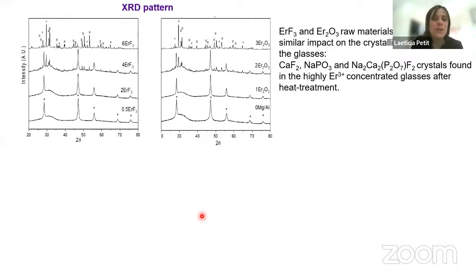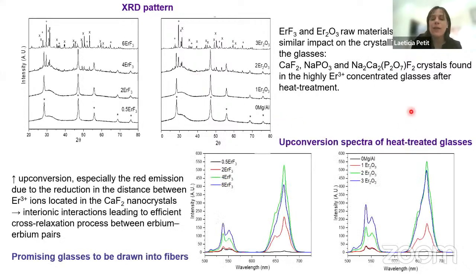So we did some XRD analysis after the heat treatment, when we try to make the glass ceramic. And we do have the calcium fluoride crystal in all the glasses, but when we increase the erbium content, we also have some other crystals growing. But more importantly, we have here the upconversion spectra of the glasses after heat treatment, and we increase a lot the intensity of the upconversion after heat treatment.